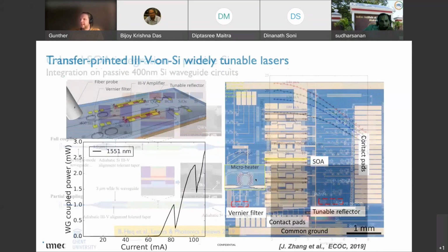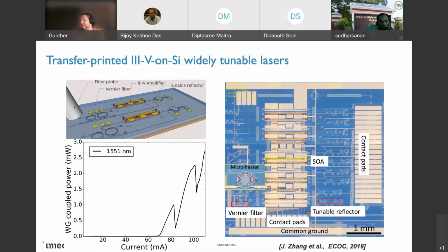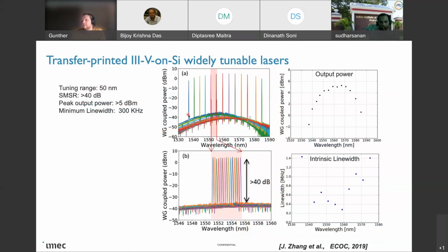Based on this technology, we demonstrated the first widely tunable lasers using microtransfer printing. Here you see a schematic of the laser. You have silicon filters that form the laser cavity. You transfer print III-V SOAs on top, and then you post-process the metallization. That was done in 2019, where we showed normal behavior for these kinds of devices: a tuning range of about 50 nanometer, good SMSR, side-mode suppression ratio, and a few milliwatts of optical output power.